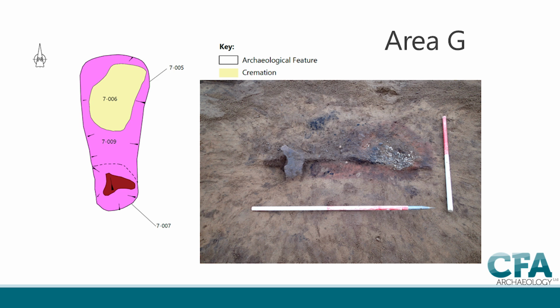The base, as you can see, is very scorched red, and there was a very thick layer of burnt cereal grain and charcoal deposit above it, which is probably the remains of the last firing of the kiln, and that could be why it fell out of use if there was a burning activity. The cremation itself was placed above the burnt grain at the north end of the kiln, which you may have seen in both the picture and the drawing.